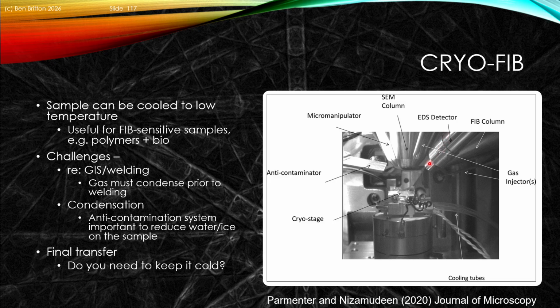systems. We'll see some important details in a short moment, that there are challenges when you're using cryo, specifically with regards to the gas injection system, because effectively you can get condensation of the gas all the way across the surface of your sample. You can also get condensation of, say, water on the surface of your sample and frosting, and so the anti-contamination system is important to reduce water and ice of this.